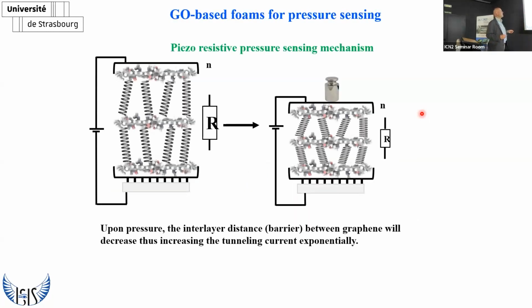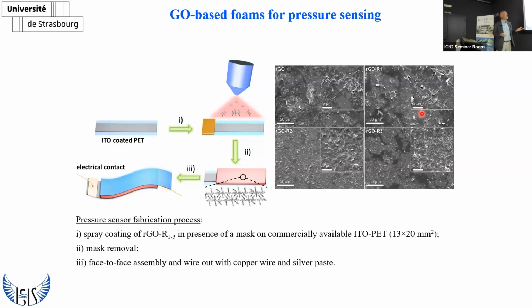So this is a kind of vertical junction we fabricated, a very simple device architecture. The way we fabricate it, we took commercial A5 foils of PET with ITO, and we cut small rectangles of 13 by 20 square millimeters. We spray coated on top of the surface this functionalized reduced graphene oxide, and we did this on the two surfaces. Then we closed them like a sandwich, a 3 micrometer thick film here and a 3 micrometer thick film here, and we wired up with copper electrodes. So essentially we have an active layer that is 6 micrometers thick.